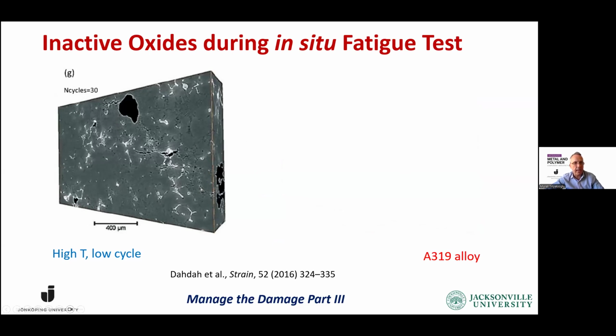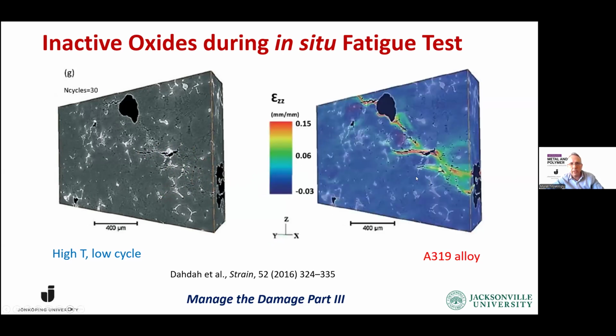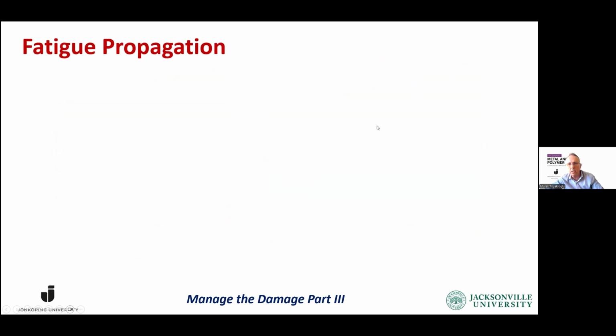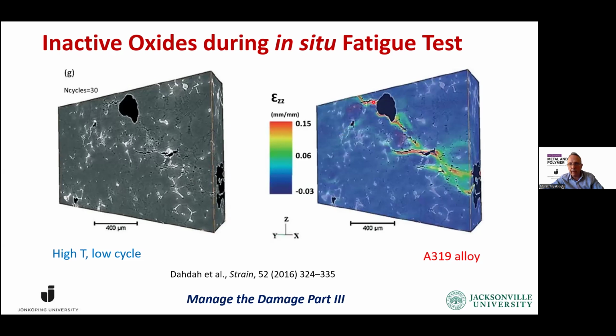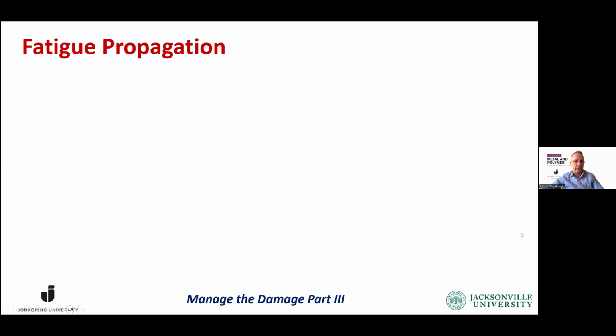And at the 30th cycle, you can see one crack here that already started propagating, but there are also multiple cracks that are opening up, and they started to propagate as well in the direction that's most advantageous for them to release the energy. If you look at the strain field at the 30th cycle, you can see a crack that has already started propagating from this pore. There's another one that is going inside. A third one that propagated here. There are many other cracks that have started propagating. And obviously, in the end, you can see that those cracks will all join together to form one large crack.